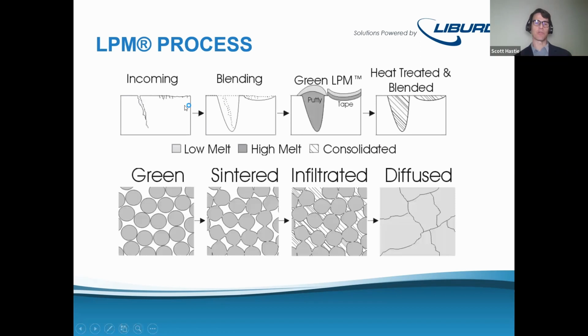So I'll step into the process a little bit here. In the top left corner, you're going to see at incoming, this represents a deep crack, and this represents some corrosion or oxidation damage on the surface. And so the difference from typical braze processes is that we'll actually remove all of the damaged material all the way to the bottom, and we'll also do additional inspections to make sure that crack is right out of the material, and then make sure we're also removing any of the denuded material on either side of that crack.